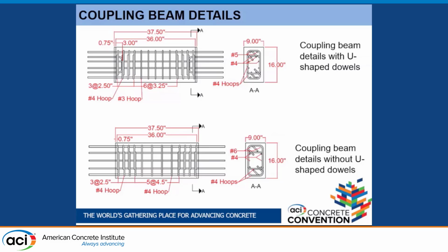We evaluated first the use of these U-shaped dowels to increase the shear transfer capacity at the interface. We expect very large rotations at the interface, so we were concerned about having a sliding shear failure that would occur prematurely. Towards the end of the testing program, we evaluated a similar detail but without the U-shaped bars, making sure we have enough longitudinal steel to achieve sufficient shear transfer through shear friction at the interface. So when I say with U-dowels, that means the detailing at the top. If I say without U-dowels, that means the detailing at the bottom.